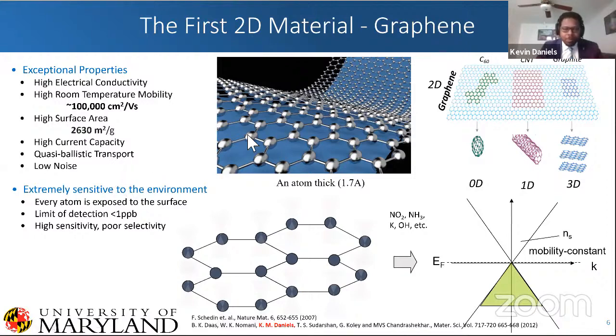And like I said, this graphene really can be seen as just a two-dimensional material, but really it's just from bulk graphite, right? In fact, the first isolated graphene was basically done by Scotch tape by Andrei Geim and Konstantin Novoselov, who exfoliated by basically taking Scotch tape to the material, and they were able to isolate a single layer. Now, this existence is really actually counter to theory, basically saying that, hey, if you heat up this material, the lattice vibration would rip this material apart if it's two-dimensional. There's nothing to support it. But graphene is great because the carbon-to-carbon bonds here are actually 4 times stronger than steel. So it's actually able to withstand that vibration of the atoms at room temperature.